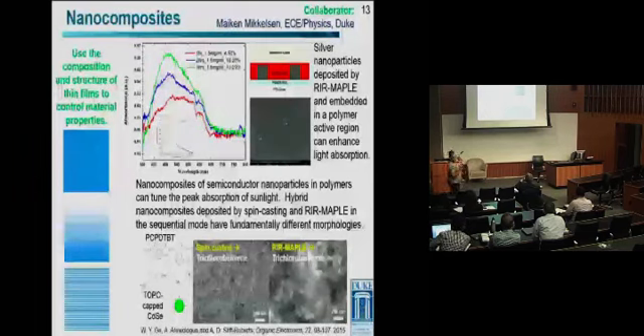And one thing that's unique about MAPLE, as I'll show more clearly here, I'll go ahead and talk about it now. So with the hybrid nanocomposites, we get a fundamentally different morphology by MAPLE, right? If you compare to spin casting. So this is a cadmium selenide nanoparticle embedded in that same low band gap polymer for solar cells. And looking, using as the primary solvent, trichlorobenzene, a spin-coated film and a film deposited by RIR-MAPLE. The scale bar here is 200 nanometers. These are transmission electron microscopy images.